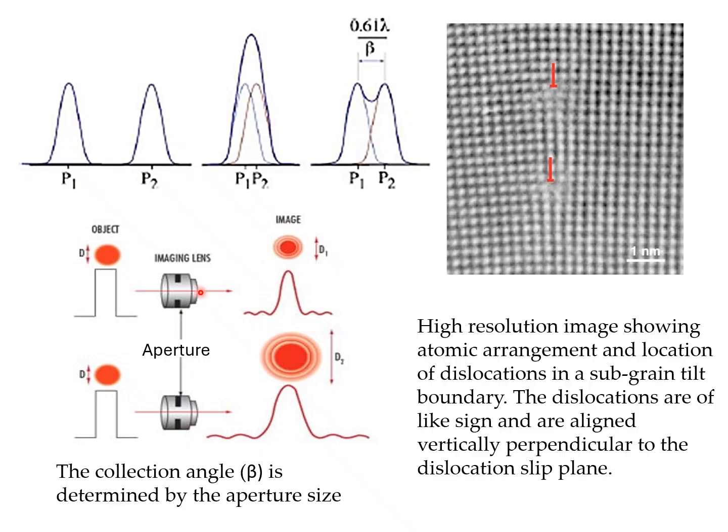And so we want a large aperture for high resolution to image atoms, typically in the electron microscope. The resolution limit is not dictated necessarily by the width of this peak, but by being able to distinguish, when you have overlapping peaks, what is the minimum separation that one can tolerate, where we can still distinguish between these peaks. And that's the expression that dictates this resolution limit: 0.61 times lambda over beta, where beta is the semi-angle of the collection angle of the aperture.